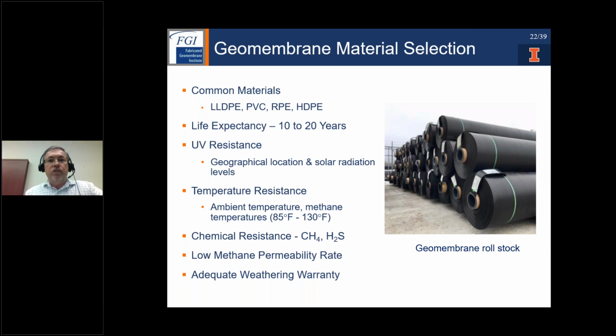Moving on to the geomembrane material selection, the most common materials that we're seeing in these fabricated geomembrane digesters are linear low density polyethylene. We're seeing PVC, both unsupported or unreinforced and reinforced. We're seeing reinforced polyethylenes. We've seen EPDM rubber, and we do see some HDPE being used as well, although they are quite stiff semi-crystalline materials with low yields. So we have to go very low tensile yields. So we have to go very thick with those materials.